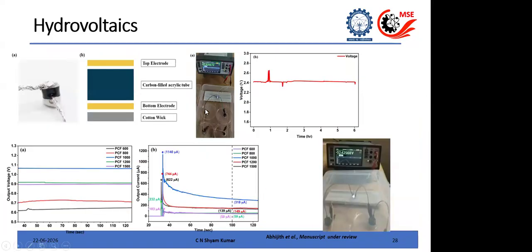And we just looked at again different possibilities and things. So this is what I want to show you. In the first case, we saw that as the pyrolysis temperature increases, the piezoresistive response is coming down. And in the case of EMI shielding, we saw that when the temperature is increasing or the graphite content is increasing, we have an improvement in the EMI shielding. Now, in this case, we have samples from 600 to 1500. So we increased the pyrolysis temperature, and we went beyond 1000. We went to some other institute where the facility is there, and we heated to 1200 and 1500.